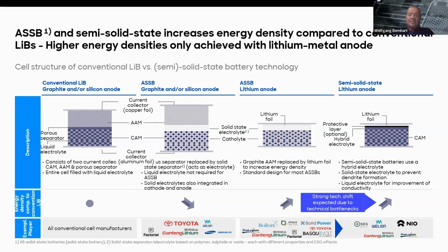Then a second topic that's being typically explored together with other approaches is a graphite or a silicon anode, or a high silicon anode. So again, you have the current collector, you have on both sides the cathode and anode active material, and you have a solid state electrolyte that could be a separator electrolyte based either on polymer, on sulfide, or on oxide. All those have different properties and different effects. The energy density compared to conventional lithium-ion batteries, with graphite it could be lower, but with silicon it can be higher. And then you have the ASSB with lithium anodes, actually as either full solid state or as semi-solid state.